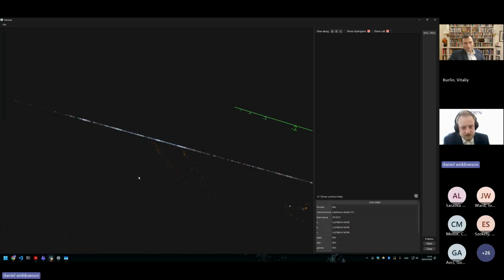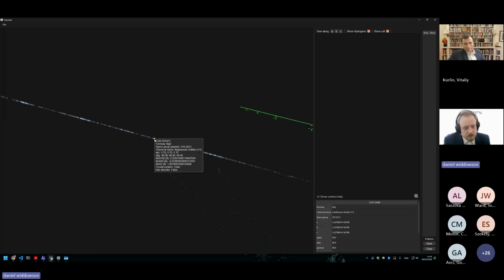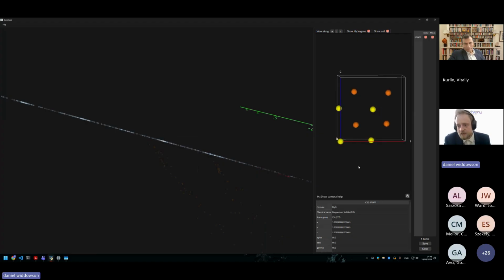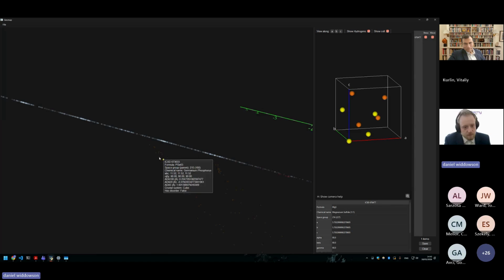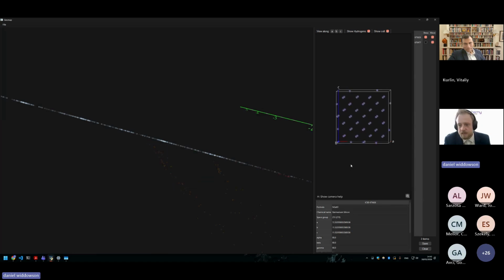So let's look at this, because this is really the crux of our invariants. If I look at this, that's exactly what the diamond structure would look like if it was all carbon. And then this has twice as big a unit cell. Almost like it's just been extended, but it's off the line. If you were to literally just double this unit cell, it should remain on the line because the structure has not changed.